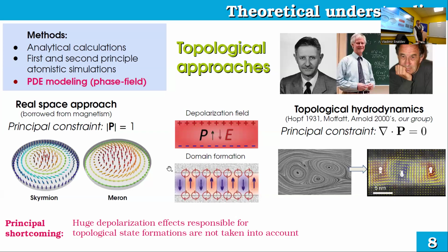Consider this example. You have some slab of ferroelectric material, let's say a thin film. It's uniformly polarized, up or down, doesn't matter. At the termination of polarization at the surface, there are huge bound charges. They create a depolarization field and it destabilizes ferroelectricity. To avoid this energetically unfavorable configuration, the ferroelectric forms domains to get rid of these bound charges. It looks more like Kittel domains, but actually in ferroelectrics there are special terms, so-called soft domains, because you also have rotation of the polarization vector near the surface, an additional rotation.